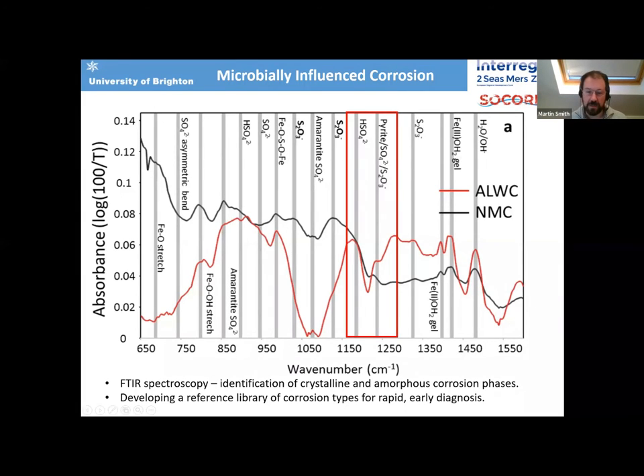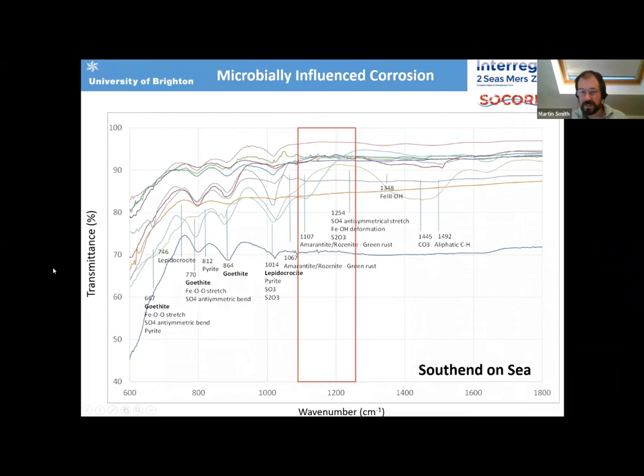And I can say that because the more recent data, so this is in transmittance rather than absorption, because this is relatively recent data. Biji Shibalal is a postdoc working on this at the moment, who also I think is here today. But this is from Southend-on-Sea. And the important thing here, just flip the axis in essence, because this is unprocessed infrared spectroscopy data, is we're seeing lots of goethite, we're seeing lepidocrocite, we're not seeing those strong sulfide and sulfate absorption bands.